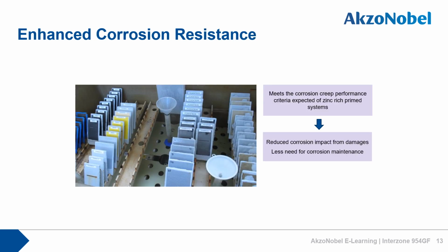We've discussed previously the enhanced corrosion resistance that glass flake pigmentation provides. This has been borne out by the fact that Interzone 954GF has shown exceptional results in accelerated tests. In fact, in the pre-qualification tests for NORSOK, it performs to a level that meets the criteria expected of zinc-rich primed systems, which gives us the confidence that it can provide very long-term durability in the harshest of environments.